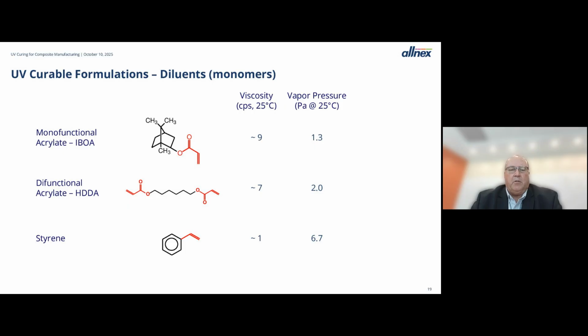If we look at a couple typical monofunctional and difunctional acrylates, isobornyl acrylate and hexanediol diacrylate, they also have very, very low viscosities and very, very good diluency, but the vapor pressure is a lot lower. So the odor and volatility are much, much lower compared to styrene. So if you're thinking about going styrene free, these are two materials that you might want to take a look at as starters.